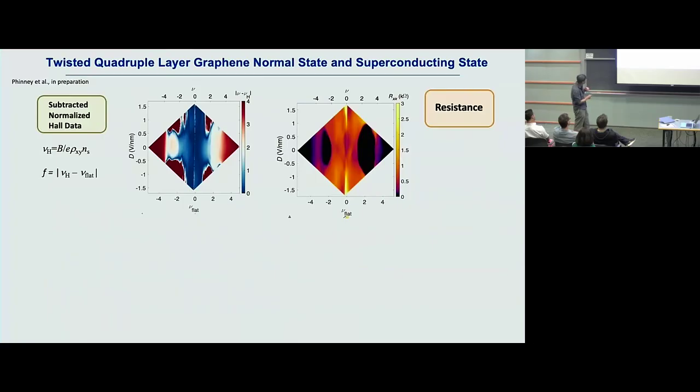Note that as we increase the displacement field, eventually this broken state goes back to the normal single-particle states, changing its degeneracy number from 2 to 4. That's because as you increase the displacement field, eventually the flat bands start to hybridize, the bandwidth becomes larger, and they mix together and become a normal band. That's usually seen in the Hall measurement.